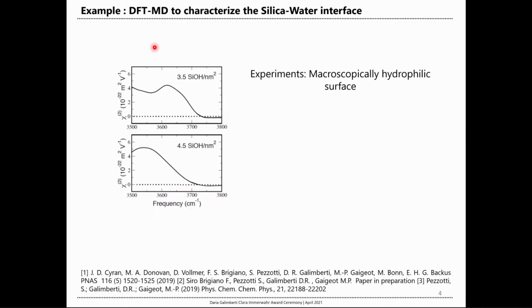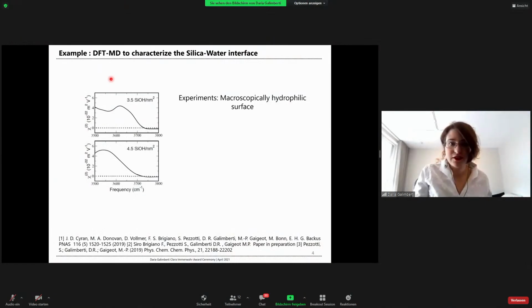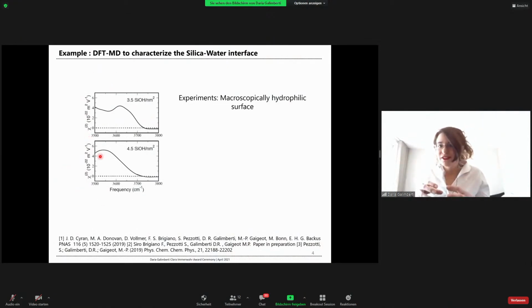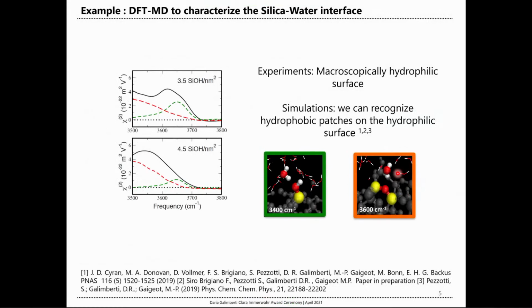And in this, simulation can give a lot of help, because we can really go and see the molecules, how they are organized, what they are doing. For example, for the silica interface, what we can see with simulation is that while macroscopically they are both hydrophilic surfaces, strongly hydrophilic, there is no doubt about this, if you look at what is really happening at the microscopic level, you will see that a change in the degrees of hydroxylation brings the emergence of some small hydrophobic patches, these siloxane bridges, that in turn will make a change in the structure of water in contact with the silica surface. And since both the surface and this water layer are changing structure, you change the chemical properties of these interfacial layers, and so change the energetics of the reaction that happens there.